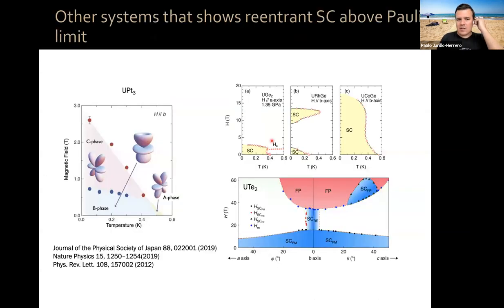Yeah. Now, there are a few superconductors which exhibit reentrant superconductivity above the Pauli limit. The most famous are the family of uranium. You know, these are radioactive superconductors, literally. So it's a family of uranium superconductors: uranium germanium 2, uranium rhodium germanium, uranium cobalt germanium. Okay. They exhibit superconductivity above the Pauli limit, and most pronounced in this case, with a big reentrant at high field. Lately, the latest member of the family is uranium ditelluride, which exhibits a super high field reentrant phase. Okay, in superconductivity. Here it violates the Pauli limit, and here it exhibits a field polarized phase at high field.